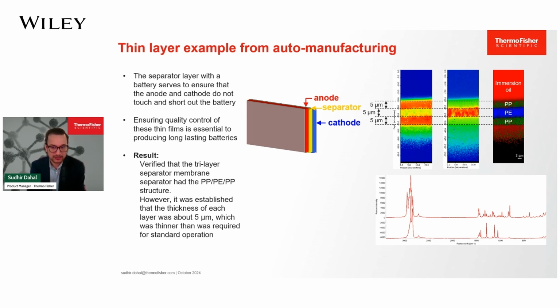As shown in the slide, Raman spectroscopy can be employed to image the separator membrane, enabling us to assess its condition and detect any potential damage that could lead to battery failure. In this particular test, as shown in the images here, the results were obtained as follows. It was a tri-layer separator membrane that was confirmed to have PP, PE, and PP, which is polypropylene, polyethylene, and polypropylene again, structure. However, although those were as expected, it was determined that the thickness of each layer was only 5 micron approximately, which is actually thinner than the standard requirements for optimal operation. So the message here is, this seemingly simple application demonstrates the immense power of Raman spectroscopy to analyze critical components, thereby contributing to the creation of better and safer batteries.